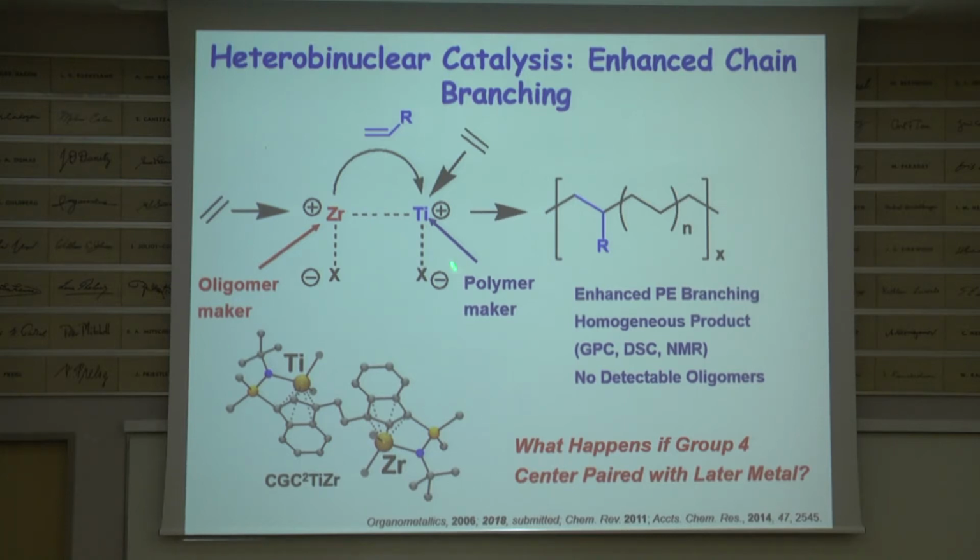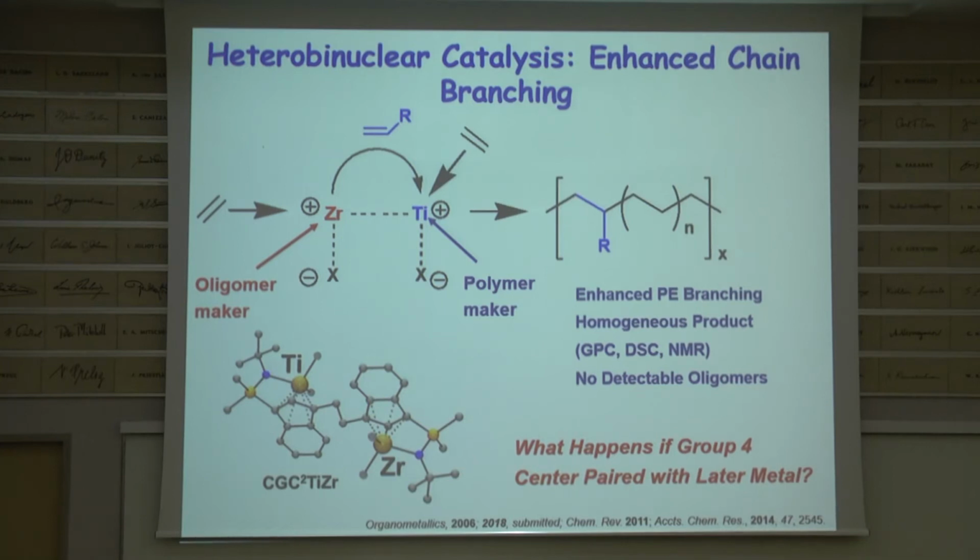And what we know about titanium is it is a very active polymerization catalyst, produces very high molecular weight polyolefins. It ravenously grabs onto any comonomers. So we've shown ethylene, but obviously it could be hexene, propylene, et cetera. More in a minute. The zirconium, on the other hand, for interesting reasons, tends to make oligomers. So relatively short chains, maybe 50 ethylenes, maybe 75, and then the chain transfer process limits the growth and it makes another chain. So I've abbreviated it this way.